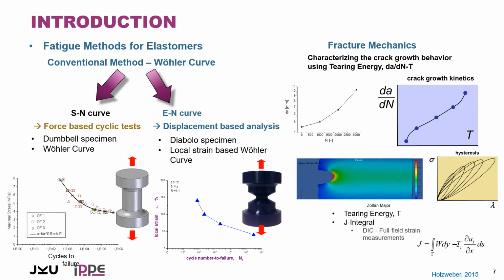It means the control parameter during the cyclic loading is not the force or the force amplitude, rather a displacement amplitude. We are typically using dumbbell cylindrical specimens, or this diabolo shaped specimen for this fatigue characterization. It means both the critical stress and also the critical strain can be used for characterizing the fatigue behavior. An additional approach is fracture mechanics based on the fatigue crack growth curve, the crack growth rate, and the tearing energy. And the tearing energy is calculated based on the hysteresis curves of the materials investigated.